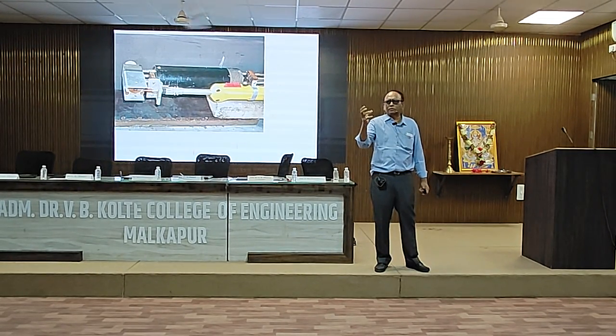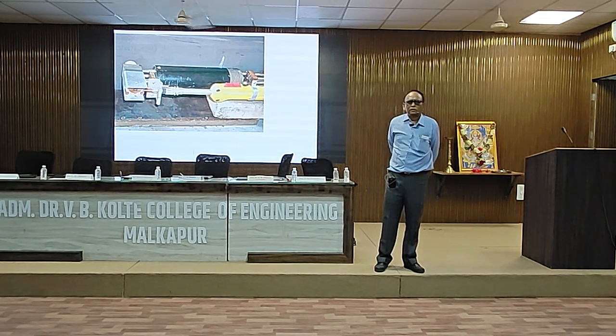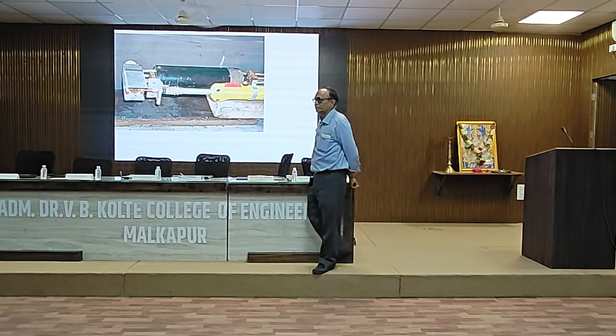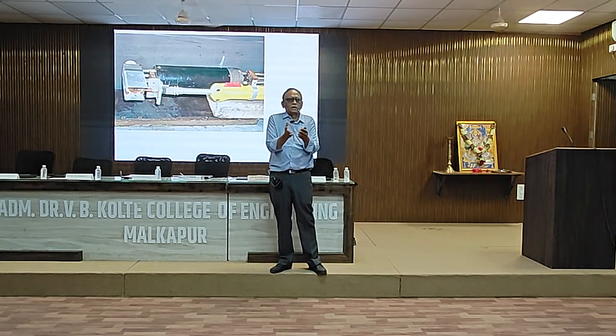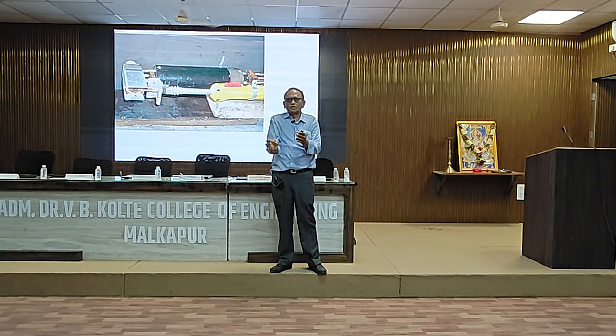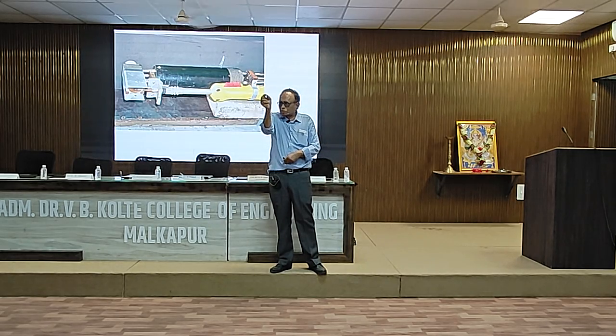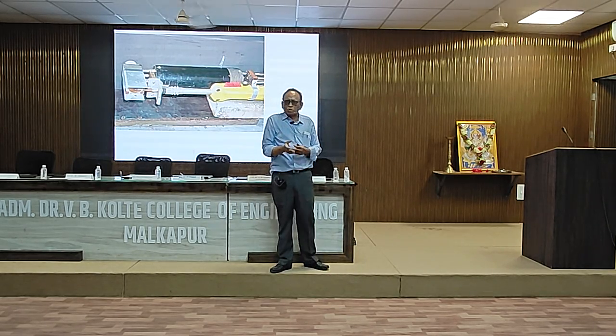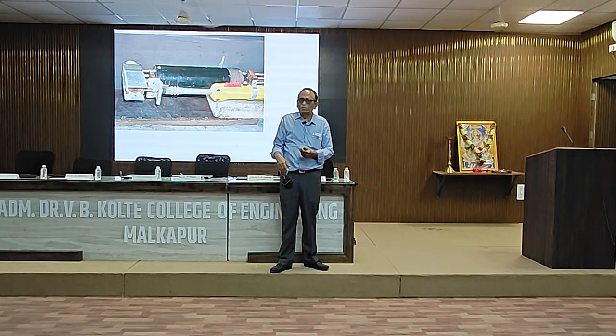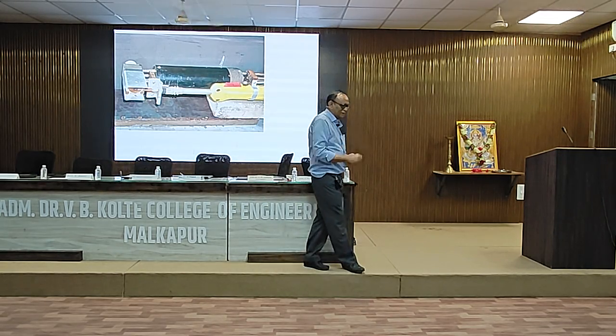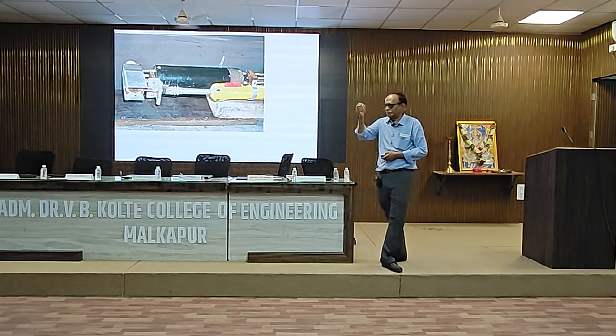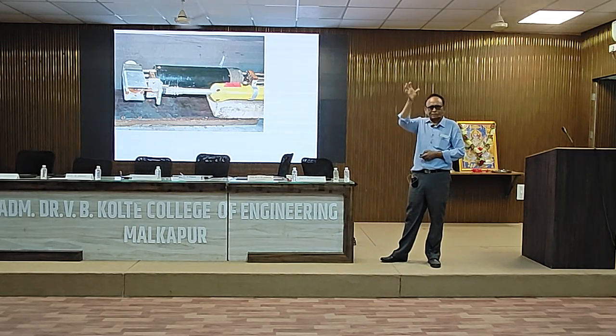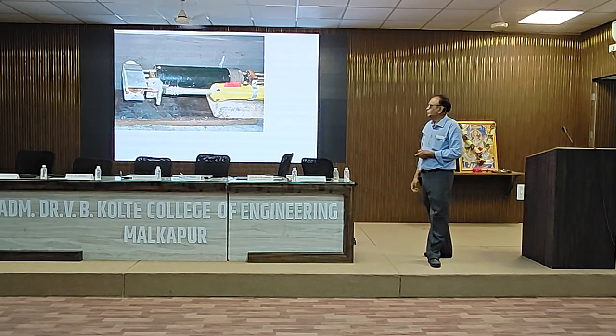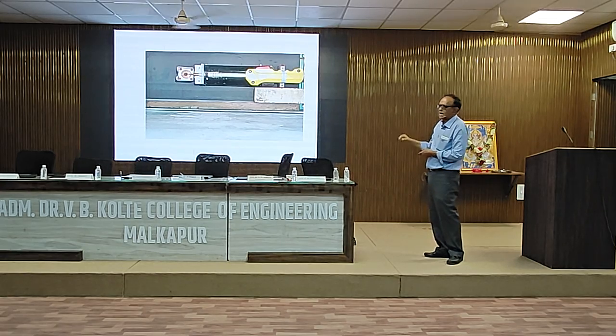Develop. Like you have seen in some of the bridges, when the pillars undergo degradation, the steel inside the pillar, which is exposed to the saline water, undergoes a lot of corrosion, and then the cross section becomes very thin. Now you cannot dismantle the bridge and redo it again. So basically, some reinforcement is done. That means for those steel bars, the corrosion layer is removed, and you put a metallic coating onto that. So again, it is an arc-based process.